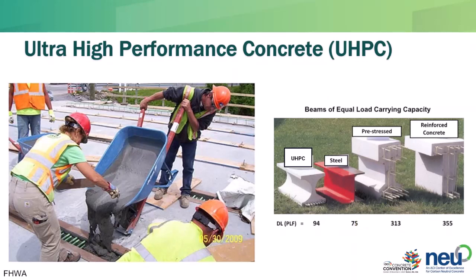Ultra high performance concrete is a big one right now. So if you're not familiar, it's very strong, very durable, very impermeable. Can get as high as like 32 KSI. Made based on particle packing, so there's no coarse aggregate at all. It's all fines, just packed really, really tight, right? Really low water cement ratio. And you can see in the picture on the left here, it behaves a lot differently than normal concrete.